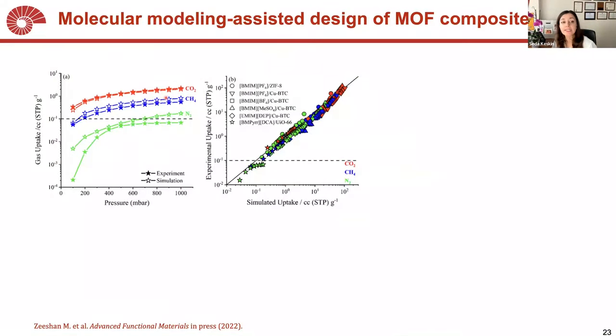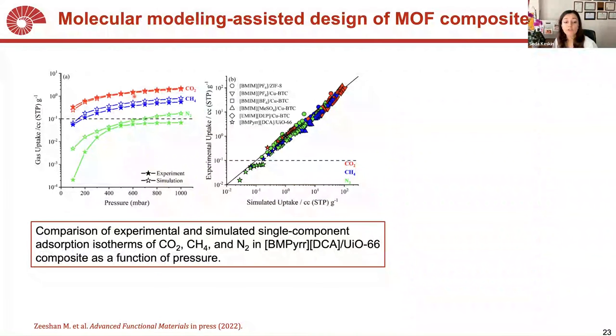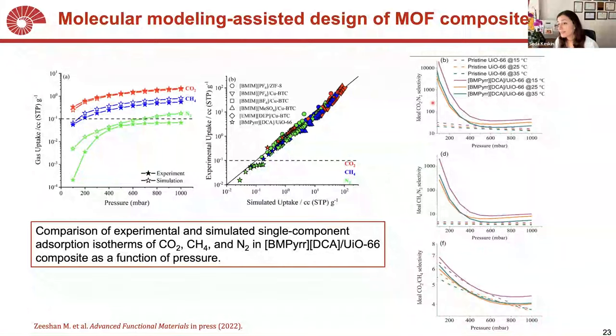And when we compare them with our previously performed GCMC simulations, except nitrogen at low pressure, we found a kind of good agreement. So the selectivity that we predicted from the high throughput computational screening was actually validated by the experiments.